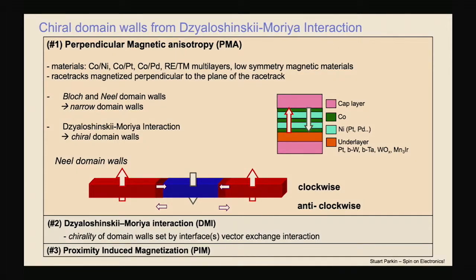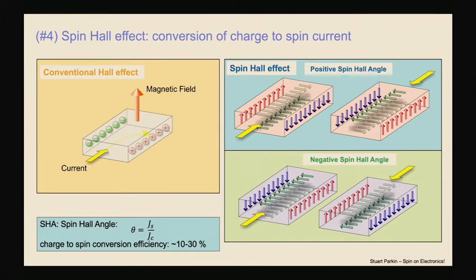But this interaction works by stabilizing the chirality of these domain walls along the racetrack in conjunction with something else you're all very familiar with, the spin Hall effect. And again, what's surprising is that this was first observed in semiconducting systems maybe 15 years ago, with very, very tiny conversion efficiencies of charge to spin current.